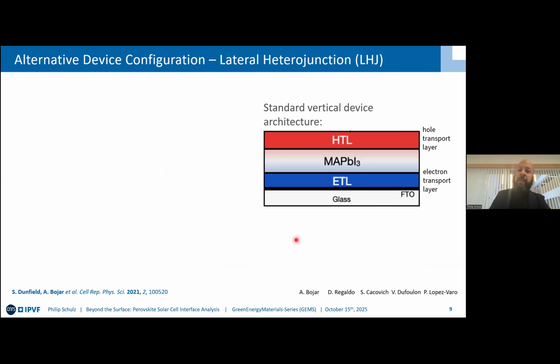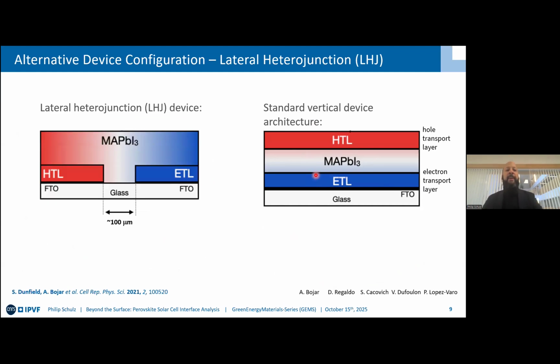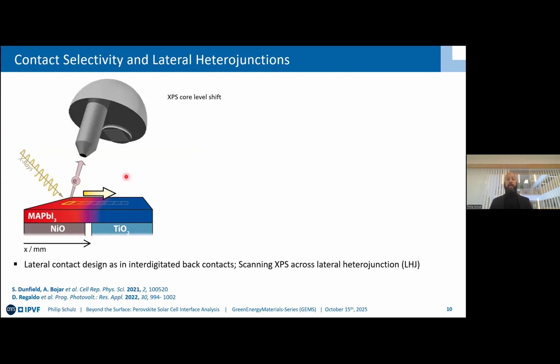And now imagine that we start off with a standard vertical device architecture, and then the interface here is buried underneath all these layers, and you will not get to it. What we did then is we flipped the script effectively and conceived this lateral heterojunction device where we have an arrangement of coplanar deposited transport layers, a hole transport layer, for instance, nickel oxide, and an electron transport layer with a gap in between. And the gap can be tens, hundreds of microns. And you then deposit the perovskite on top, and what you should then get is either Fermi level pinning, so everything at the same level, or if you have a large depletion width, you can see at the surface the formation of the p-n junction between those two contacts. And that is exactly what we're looking at.